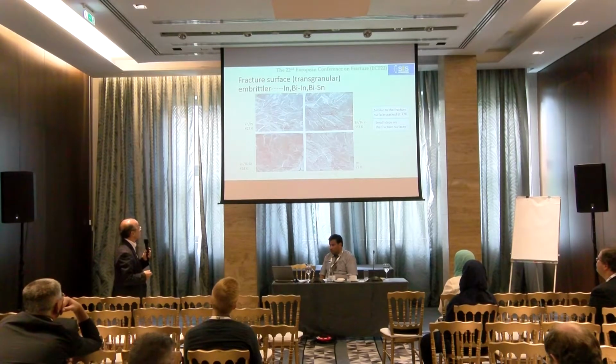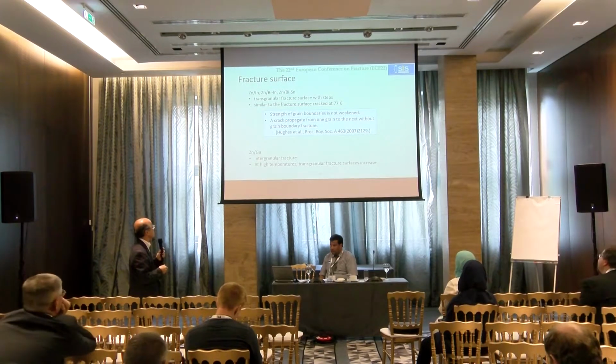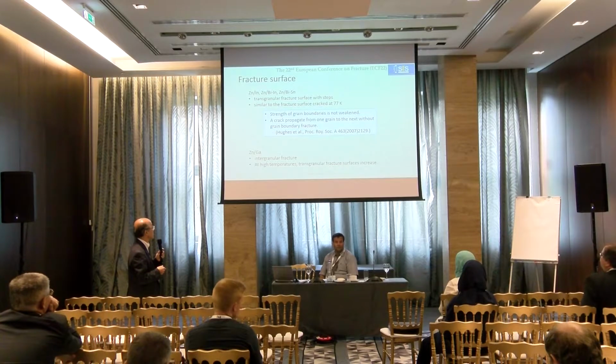For comparison, this is a fracture surface cracked at 77 degrees without any embrittler. This stepped cleavage is very similar to this one. In the fracture surface cracked at 77 degrees, the stepped surface is created because a crack propagates from one grain to the next without grain boundary fracture.